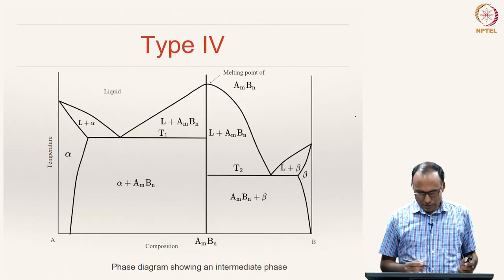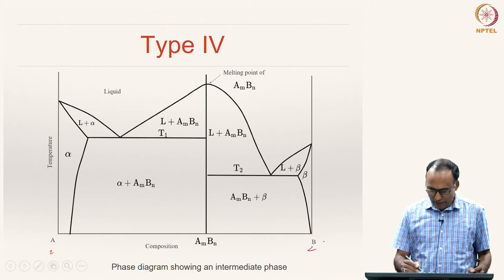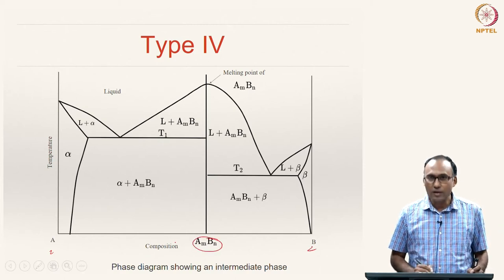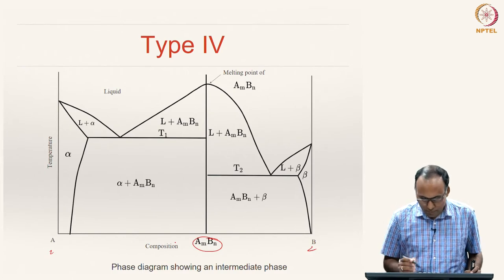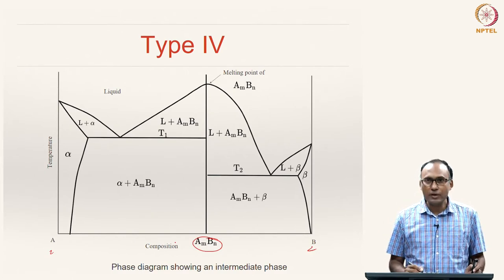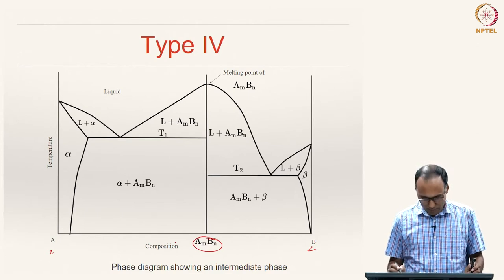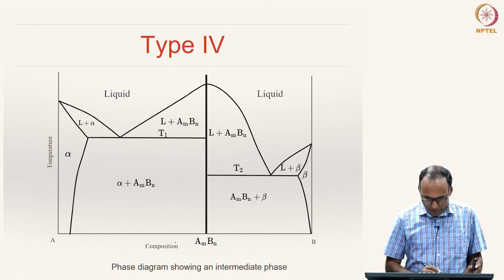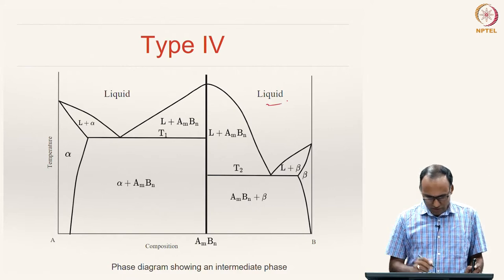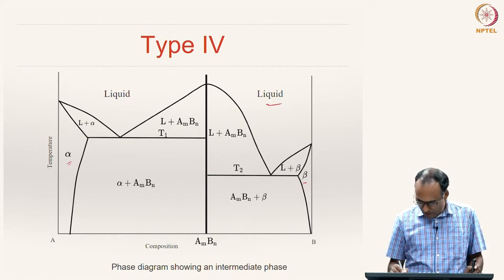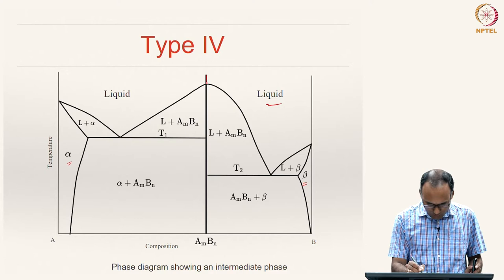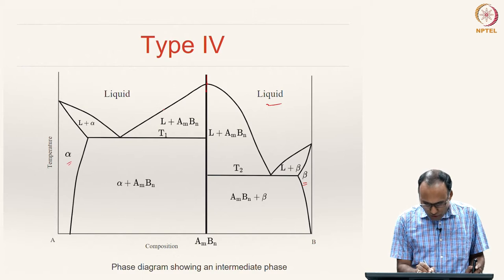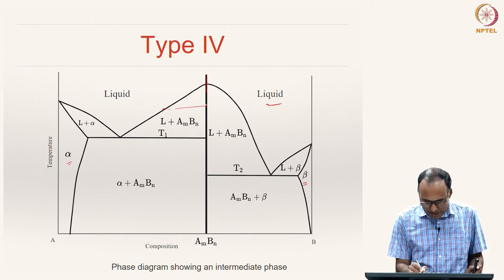If we have A and B and A_M B_N is our intermediate compound which is melting congruently, we can actually view this phase diagram as two different phase diagrams. On the left you have a liquid phase, the terminal solid solution alpha, and on the right another liquid phase with terminal solid solution beta. Because this intermediate phase has a higher melting temperature, when you are solidifying it will solidify into the special compound A_M B_N. If you draw a tie line on the left side, you have liquid and A_M B_N, so the two-phase region there is liquid plus A_M B_N.